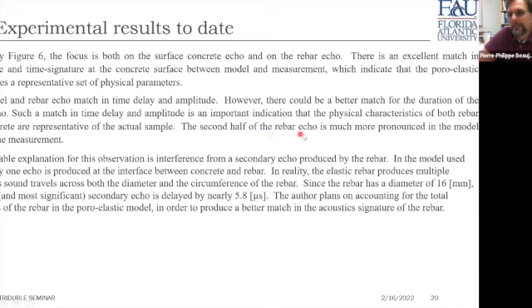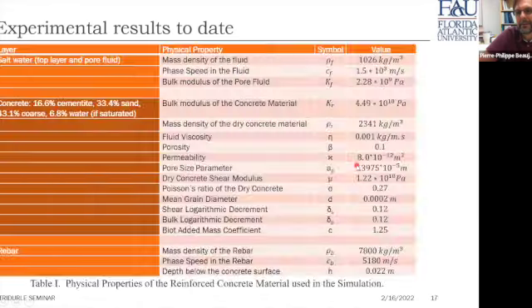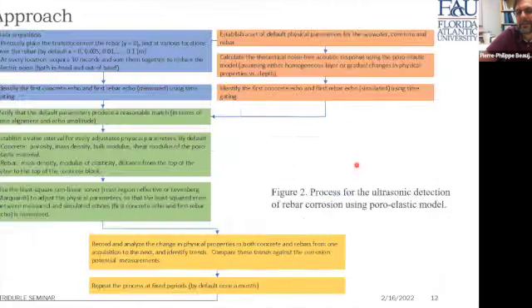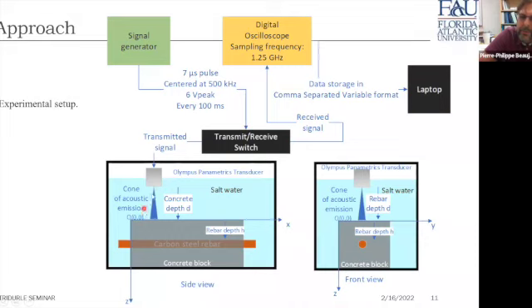The second half of the rebar echo is much more pronounced in the model than in the measurement. And there is a reasonable explanation for that. That reasonable explanation is that for this observation, there is interference from a secondary echo produced by the rebar itself. So let me just go back to the slide and explain what I mean by this. What happens is that as the sound travels in the concrete and hits the rebar, sound is actually going to travel through the rebar and create a secondary echo at the bottom of the carbon steel rebar.